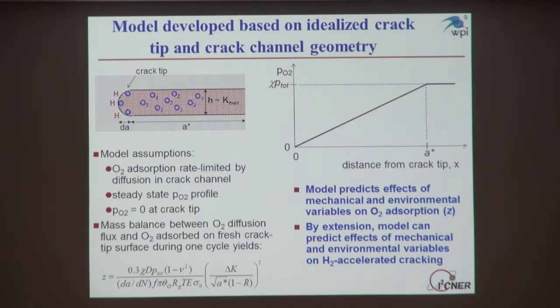And when Reiner did all of the math, it's basically a diffusion calculation. And we assume that there's a mass balance between the oxygen diffusing down the crack channel and the oxygen adsorbed on the crack tip surface. We come up with this formulation, where Z is the amount of the adsorbed oxygen. And you can see this model contains all of the experimental parameters from the data that I showed you. Parameters like the mechanical crack growth rate, the load cycle frequency, the stress range, and some others.